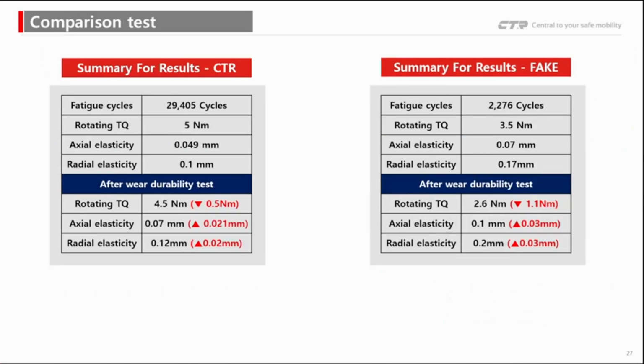This slide shows a comparison result between the CTR genuine and fake ball joint products after fatigue and driving testing. Let's look at the key figures. Fatigue life: CTR registered nearly 30,000 cycles, while the fake part failed after only 2,276 cycles. That's a huge difference in durability. Rotating torque: CTR started at 5 Nm and slightly dropped to 4.5 Nm after testing. The fake part started much lower at 3.5 Nm, and after wear testing, it dropped significantly to 2.6 Nm, indicating a loss of preload and internal wear.